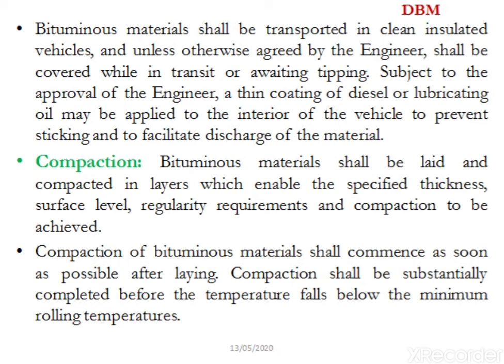Compaction shall be completed before the temperature falls below the minimum rolling temperature, that is between 90 to 100 degrees Celsius, and the longitudinal joints shall be rolled immediately behind the paving operation. After this, rolling shall commence at the edges and progress to the center longitudinally, except on superelevated and unidirectional cambered portions, where it should start from the lower edge to the upper edge, parallel to the center line of the pavement. Rolling shall be done continuously until all marks have been removed from the bituminous surface.